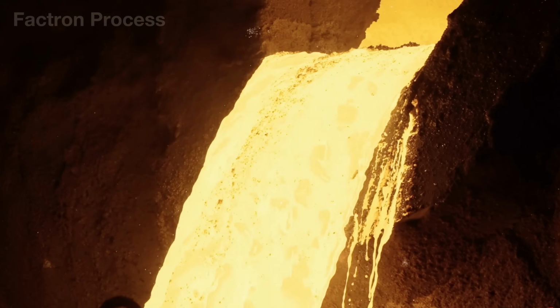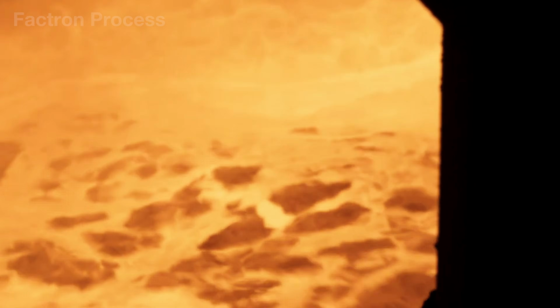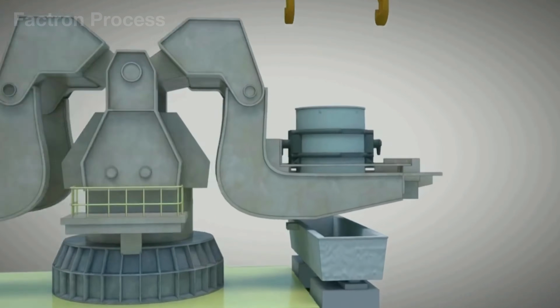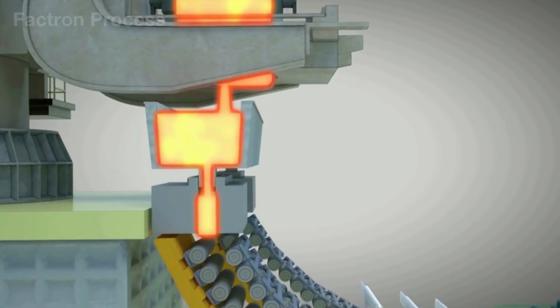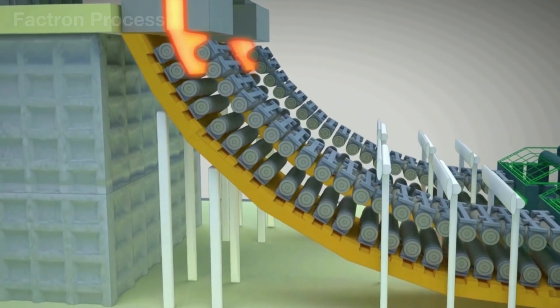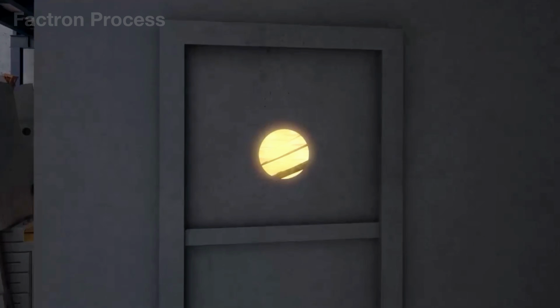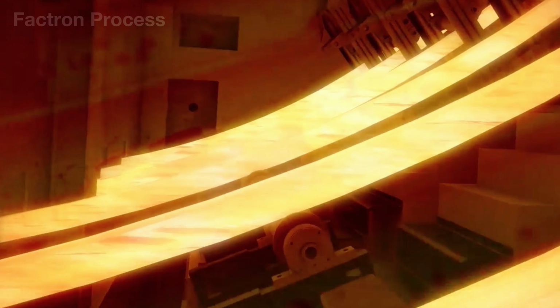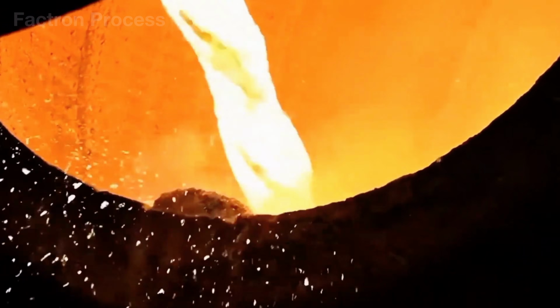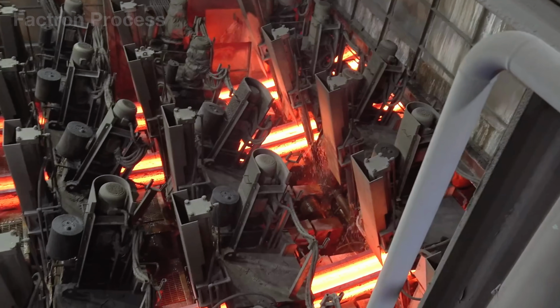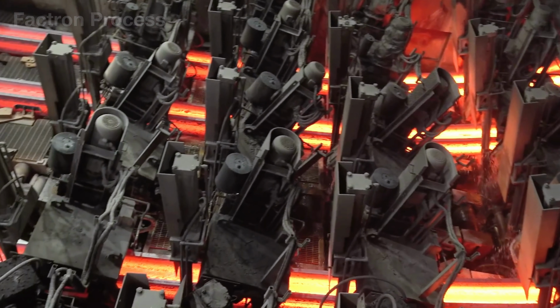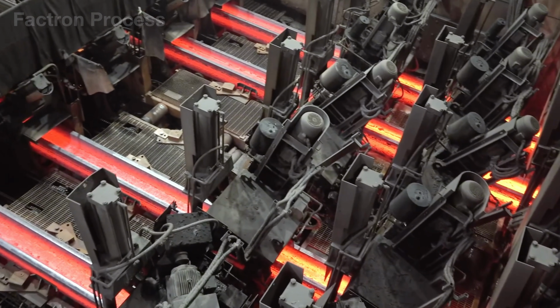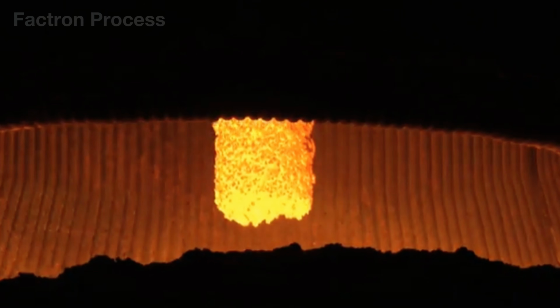The qualified molten steel is then sent to a continuous casting system, where it solidifies into large, exceptionally clean blooms. The process begins as the steel flows through an airtight submerged entry nozzle into a tundish, before descending into copper molds cooled by high-pressure circulating water. The outer layer rapidly solidifies into a steel shell, while the core remains molten.